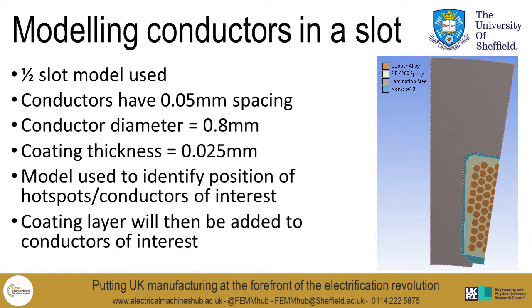So this now shows the model which we were using to represent the slot. You can see here it's a half slot model. Here the conductors are spaced by 0.05 millimeters, and the diameter of the conductors is 0.8 millimeters, as was the case in the previous models. The coating also remains unchanged at 0.025 millimeters. This model initially is used to identify the position of the conductors of interest and also where the hotspot is likely to be within the winding. After we've done that, we will then apply a coating layer to the conductor of interest to see how the stress is.